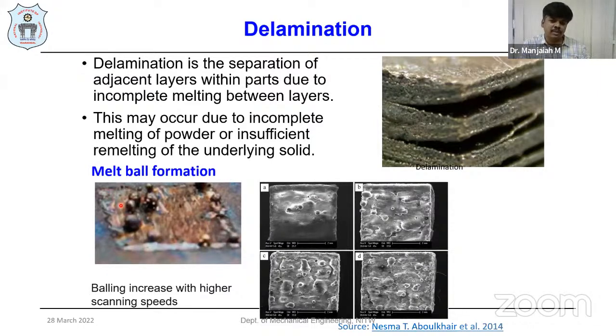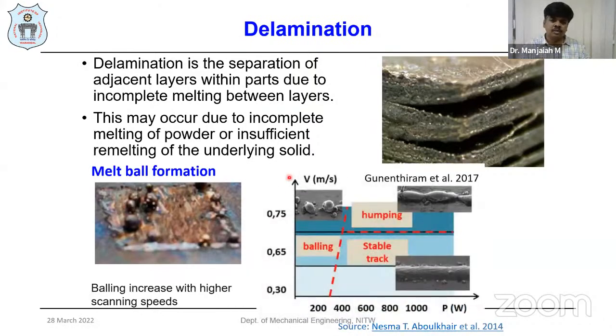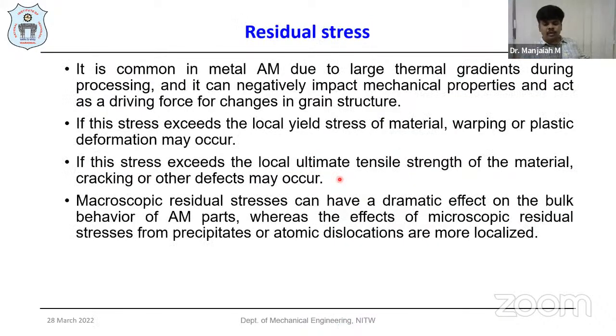If you are not optimizing the proper scan speed and laser power, these kinds of defects are going to occur. The balling defects, as well as with the higher scan speed, we are going to have these kinds of defects. You see, to have a stable track, we need to optimize the laser power as well as scan speed. If you go with very high scan speed, there may be humping, or maybe balling effects are going to be low. Even with low laser power, one has to optimize or adjust the laser power as well as scan speed.